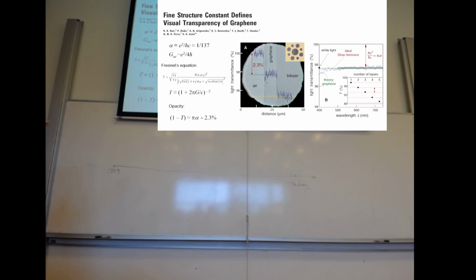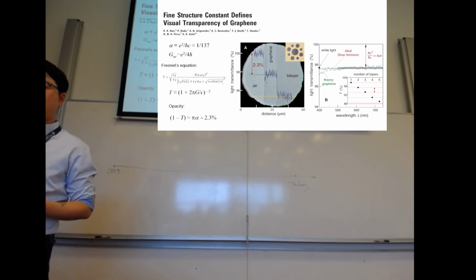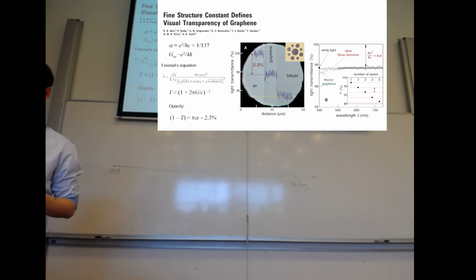Nowadays, we know that the absorption of light of each layer is actually quantized. So it's proportional to pi times alpha. Alpha is the fine structure constant. The fine structure constant is a magic number. So if you use pi times alpha, using this kind of approximation, each layer of graphene is absorbing 2.3% of light.